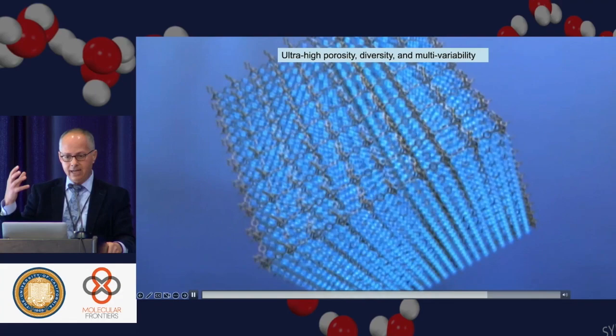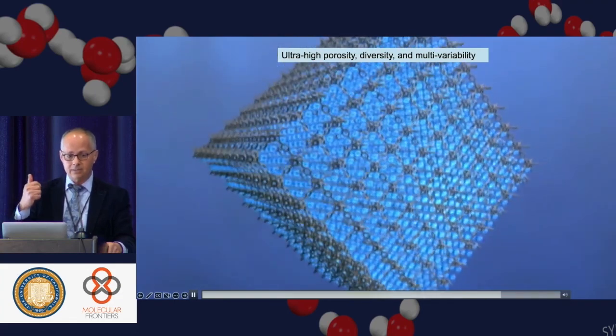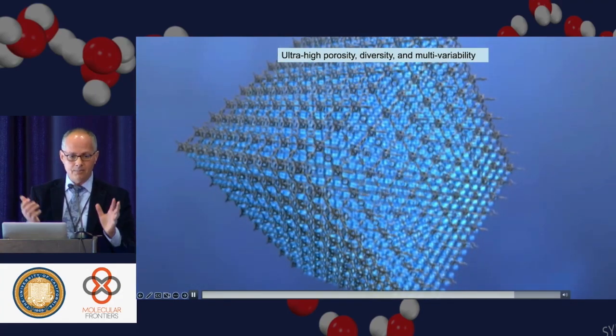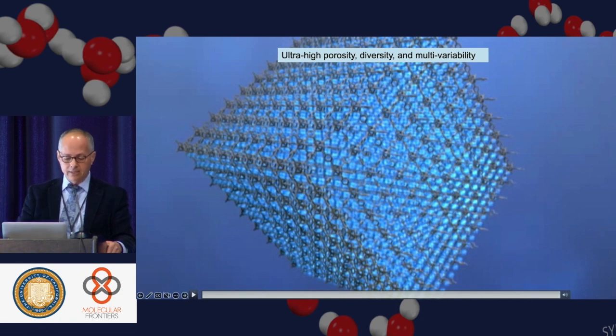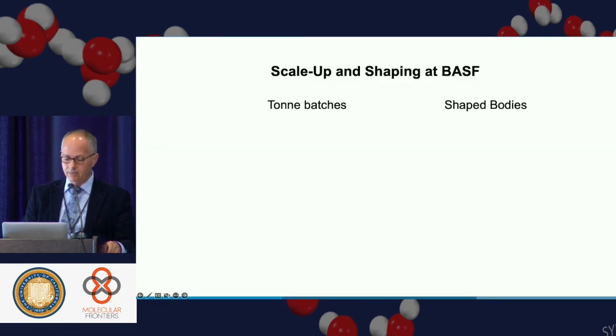So that gas, because of the adsorptive sites that are encompassed by these structures, basically gas molecules touch the surface or bind to the surface just like bees on a honeycomb. And that's why you can compact them into smaller space, foregoing the need for high pressure and low temperature.